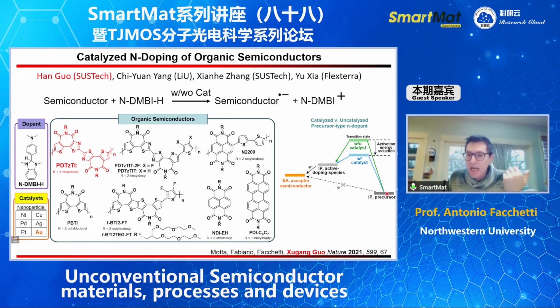Okay. And as I want to remind you, the precursors have to be converted into active species, and they have to go through a transition state, which typically is high in energy. And the idea is, if we use a catalyst, we can reduce this activation energy and facilitate the process. So how did we do this? We did this as an example using this dopant. Again, we want to break this CH bond.